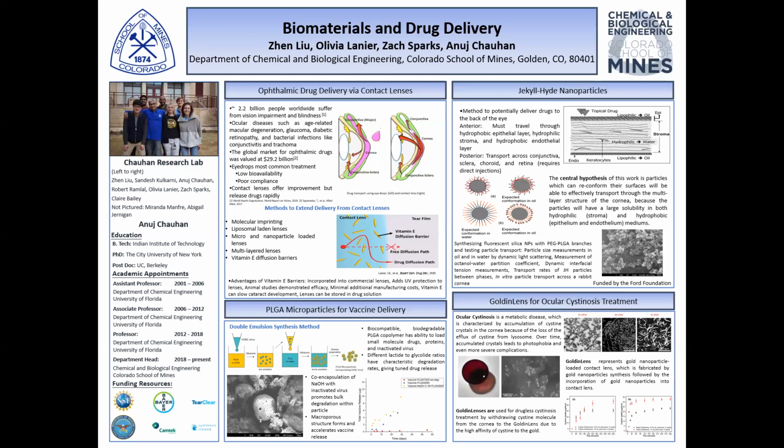This is what we call the Jekyll-Hyde nanoparticle. When it's administered to the eye, it folds its chains so that the PLGA is exposed, giving it a hydrophobic surface, which allows it to transport through the tight junctions in the hydrophobic epithelial cell layer. Once it transports through this layer, it then reaches the stroma, which is hydrophilic, in which case the polymer chains then extend to expose the PEG on the outer surface, giving it the hydrophilic nature.